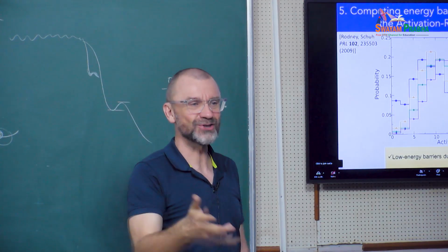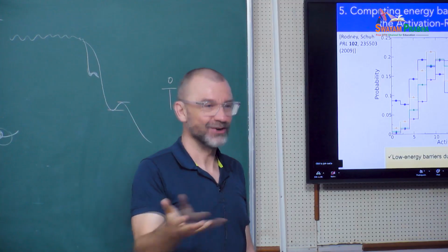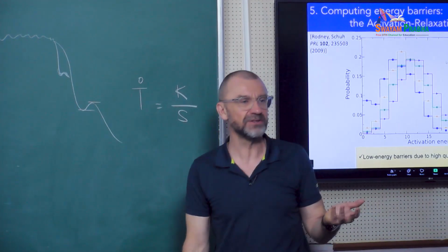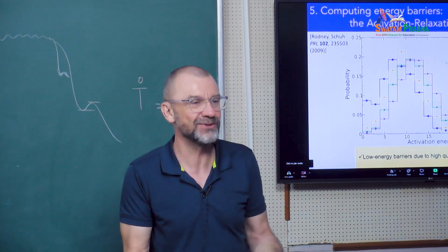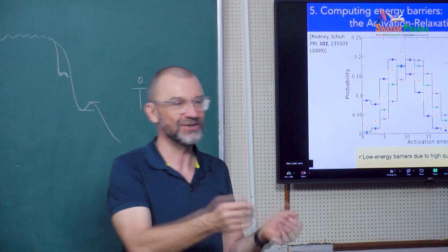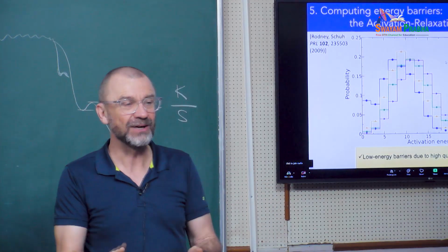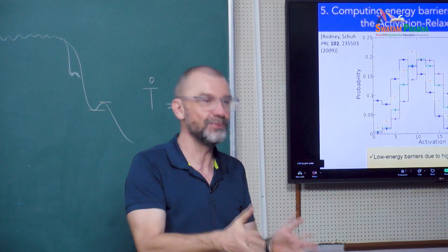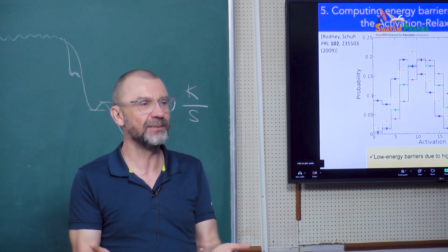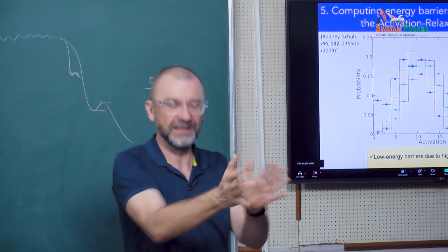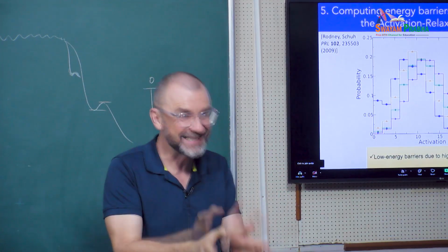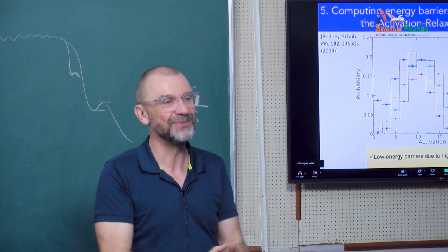Since the structure is going to be poor, you might as well use a Lennard-Jones potential. For me, it does not make much sense to use ab initio calculations on a glass, because you represent the interactions very precisely, but on a structure that has nothing to do with the experiments. Some people do, but you have to be extremely careful with what you say about what you get from your simulations.